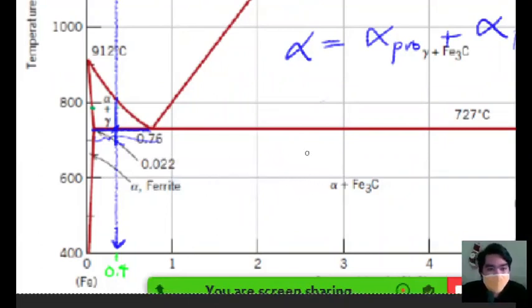And so, this is the alpha phase, sorry, it is the inverse lever rule. So this is the alpha phase, and this is the gamma phase. But the problem states that we are to determine the fractions at a temperature just below the eutectoid. So if we are just below the eutectoid, this means we are in this portion. So we are nudging it downwards, just below. Meaning our gamma has completely transformed into pearlite.